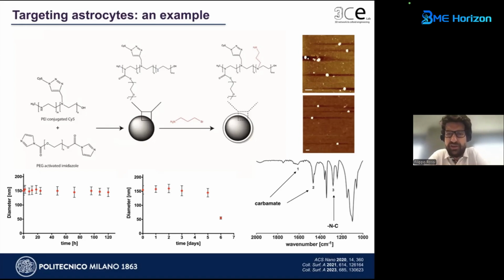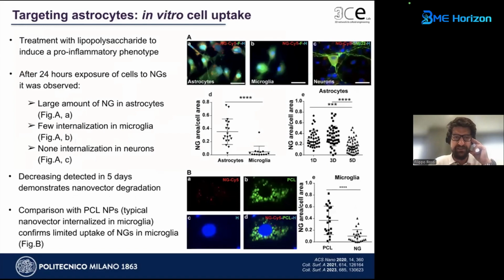So it's not a real functionalization, only a very small surface decoration after the nanogel is formed. These are how they look in terms of dimension, 150 mostly, so a little bit bigger respect to the other. The presence of carbamate group is, from the FTIR analysis, the verification of the reaction that takes place during the formation of the nanogel that is cross-linked, so a real covalent bond, while in polymeric micelles we don't have a covalent bond between the polymeric chains. And then you can see the degradation from the diameter that starts from 150 and then is reduced after 6 days. We then treated with the LPS.